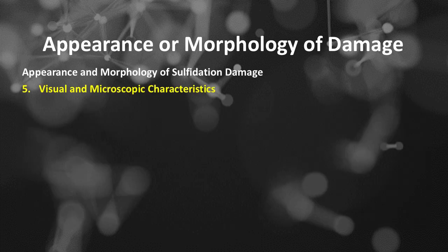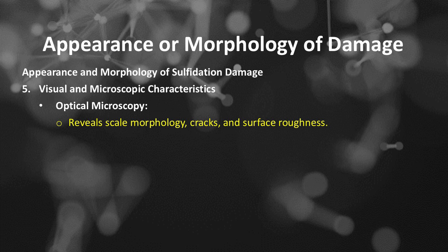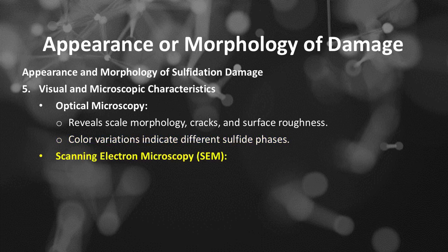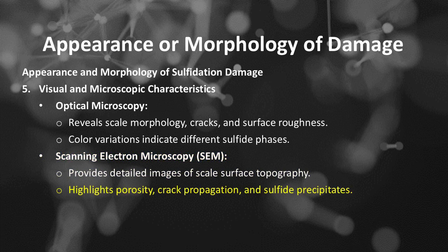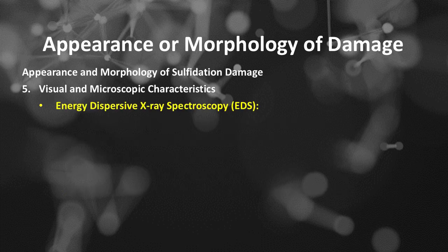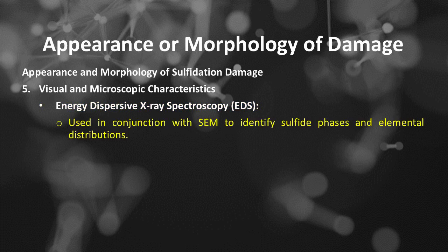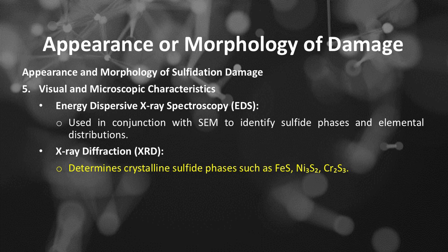Number 5 of appearance and morphology of sulfidation damage is visual and microscopic characteristics. Optical microscopy reveals scale morphology, cracks, and surface roughness. Color variations indicate different sulfide phases. Scanning electron microscopy, SEM, provides detailed images of scale surface topography. Highlights porosity, crack propagation, and sulfide precipitates. Energy dispersive X-ray spectroscopy, EDS, used in conjunction with SEM to identify sulfide phases and elemental distributions. X-ray diffraction, XRD, determines crystalline sulfide phases such as FeS, Ni3S2, Cr2S3.